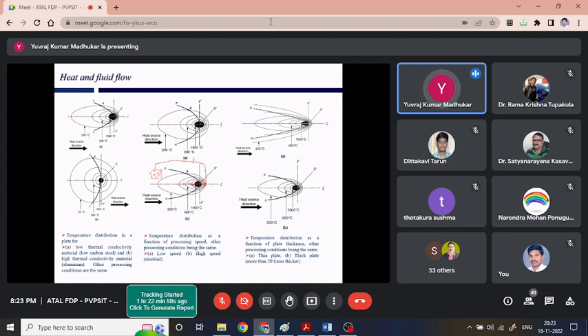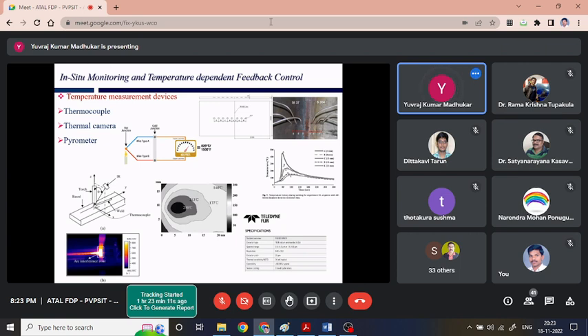We can place our sensor, since the temperature reduces significantly, but it reduces over a certain distance. So we have a large amount of area for monitoring and control. So a feedback control system seems to be a better choice for this particular case. Now, at this point of time, we know we can go for measuring the temperature in order to control our parameters. We know where we should place it. We should go for the feedback-based control system, and we should try to monitor the temperature behind the arc so that we can make the feedback-based control system, since we are getting a larger area for monitoring and control, and we are going to get a more stable result over there.